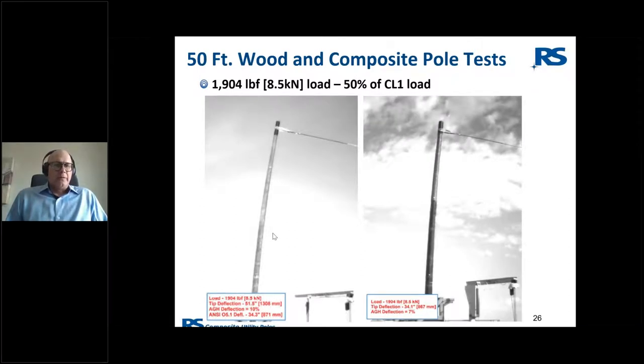Now we've got about 1,900 pounds of load, or 50% of the class one load, and the wood pole you can see has a tip deflection of about 51 inches. So trending, again, about a third or so higher than the ANSI predicted values, and that's equal to about 10% of the pole's above ground height. And over on the right, we have the RS composite pole that has, again, a tip deflection of 34.1 inches, or just below the mean ANSI deflection values. And the deflection of above ground height, sorry, is 7%.